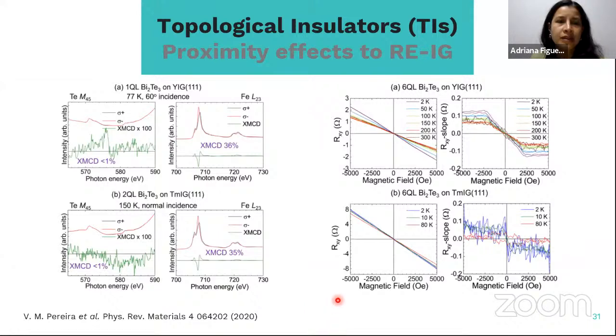But this is in stark contrast to what has been reported in transport measurements. So here I'm showing results of a recent paper. In this study, they do transport measurements where they see some features of proximity effects, in the sense that they observe anomalous Hall effect on these stacks, which will result from these proximity effects. In this case, it is a bismuth telluride interface on YIG, and they also do XMCD.